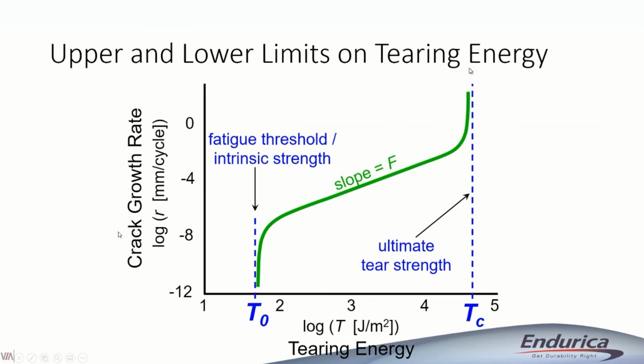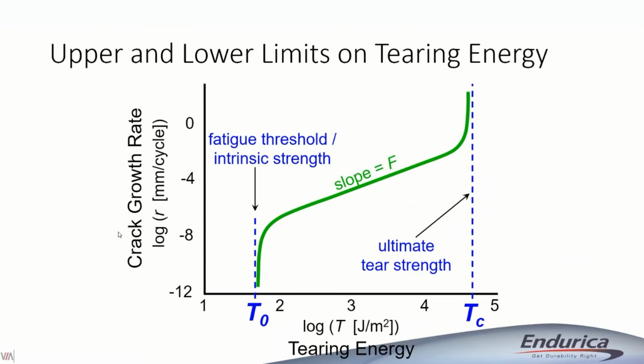Right, so rubber has a tear strength, and that's the upper bound of the crack growth rate curve. Now there's also a lower bound, and this is what we would call the fatigue limit, T naught. That's a value of the tearing energy, and if you're below T naught, then you're not supplying enough energy to the rubber or to the crack to break polymer chains that cross the plane of the crack, and so the crack can't grow. We also call this the intrinsic strength because really this fatigue limit represents the energy that it takes to break the covalent bonds of the polymer chains that are crossing the plane of the crack.